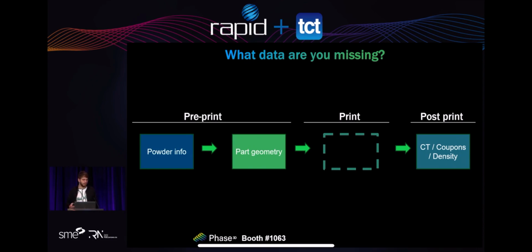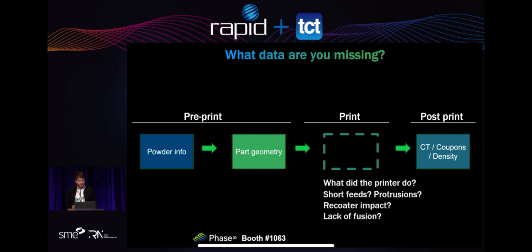It's like I wouldn't put a roast in the oven for 12 hours and never open the oven to check and see what's going on. And it really presents an opportunity to understand, what did the printer do exactly? You know, I programmed it, it has hundreds of thousands of vectors. What was the effect of the scan pattern on each layer? Were there any short feeds or protrusions in the build? Did the recoater impact the part? It probably did. Is there lack of fusion defects?